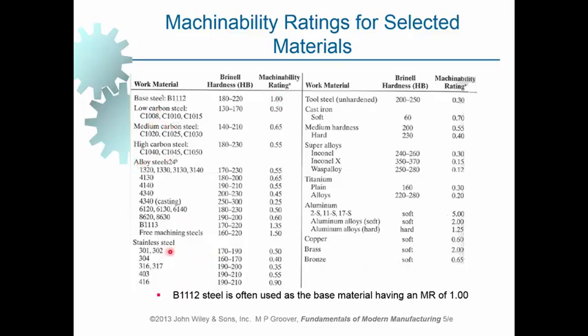Well, taking a look at this table, we can see that there are different types of steels and alloy steels, stainless steels, tool steels, cast irons, medium hardness steels, as well as super alloys, titanium alloys, aluminum alloys, and some other types of alloys including copper, brass, and bronze. Of all these, there are just a few of the materials with a higher machinability rating, and those include this steel B1113 with a machinability rating of 1.35, free machining steels with a machinability rating of 1.5, as well as alloys of aluminium. Look at this one. The machinability rating of this type of aluminium is 5, which is a highly machinable material.